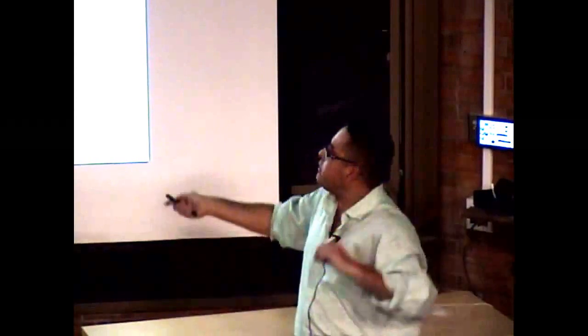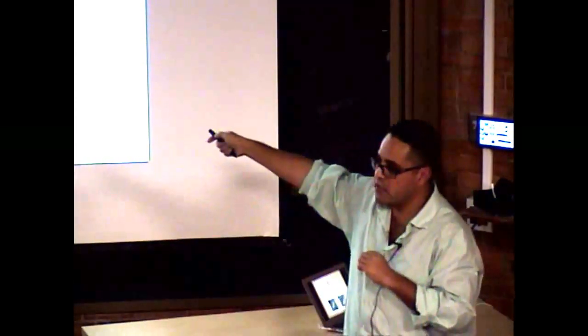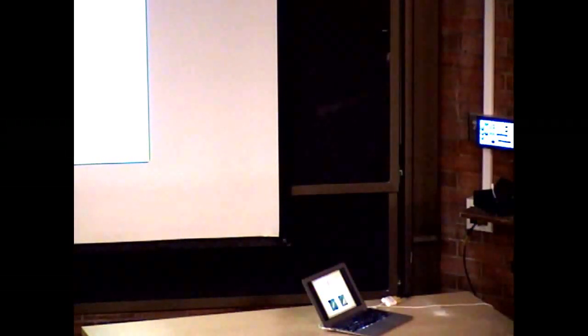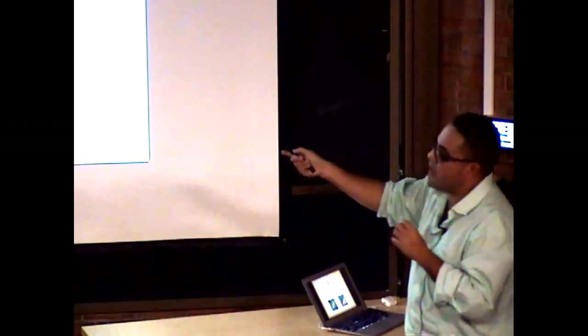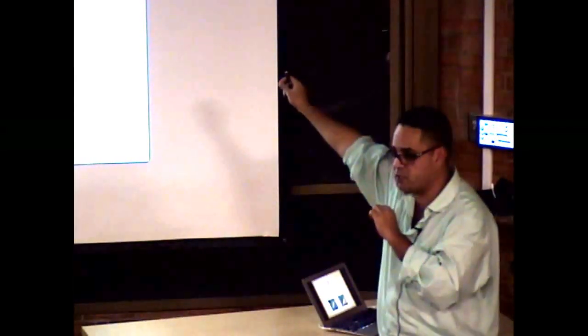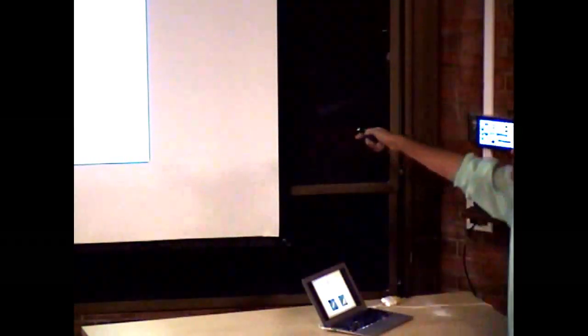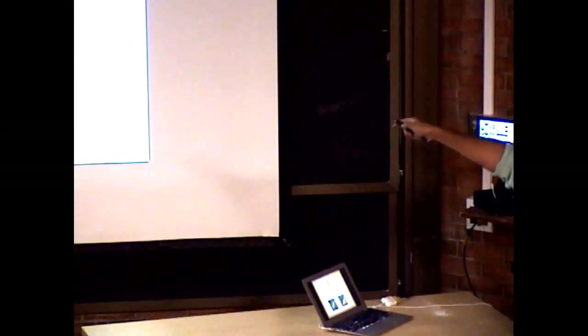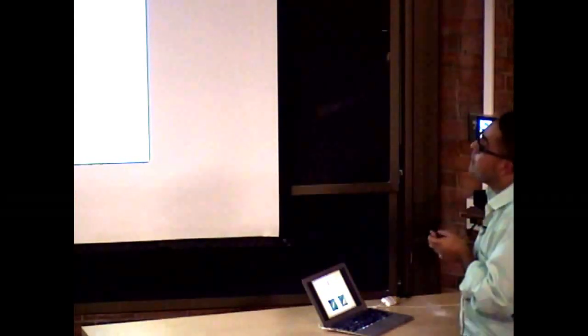But what do you measure? Photocurrent and photoluminescence? This is just photoluminescence intensity, but I can measure photocurrent. It doesn't matter how I measure it. It depends on what I'm interested in studying. But here, I want to make this connection between the photoluminescence process and the excitation process. So I'm measuring the time-integrated photoluminescence, just with a regular detector, sending it to a lock-in that's referenced to these phase modulation frequencies that I described.